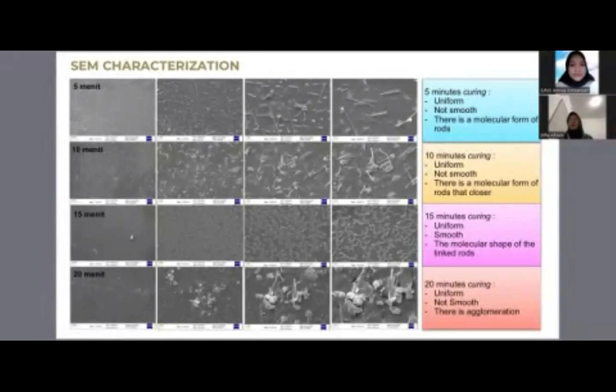This indicates that RM257 has filled the voids in the PMMA matrix perfectly, while in samples with a curing time of 5 minutes and 10 minutes, RM257 has not mixed with the PMMA matrix well, so the surface is not very smooth and causes the reactive mesogen molecules to be spaced apart. In the sample with a curing time of 20 minutes, the fineness level decreased and caused agglomeration. This was because the curing time was too long, so the thin film became like glass.